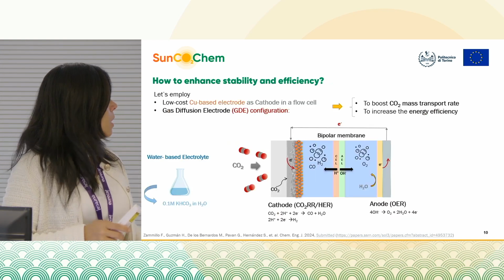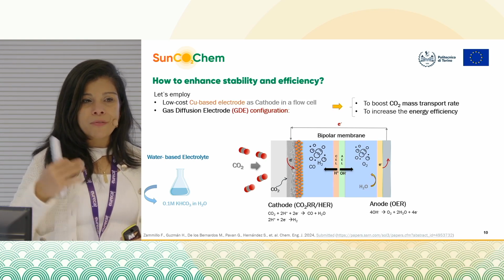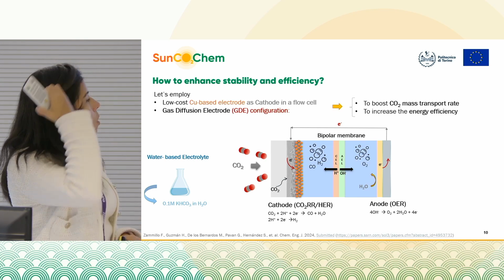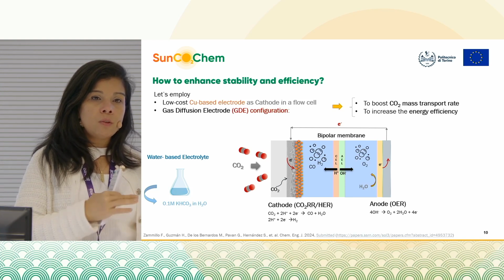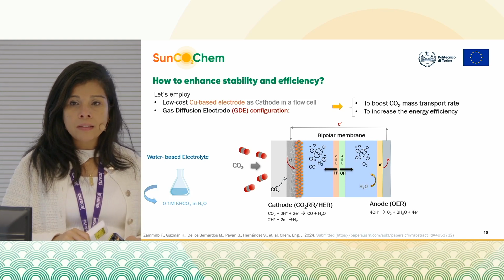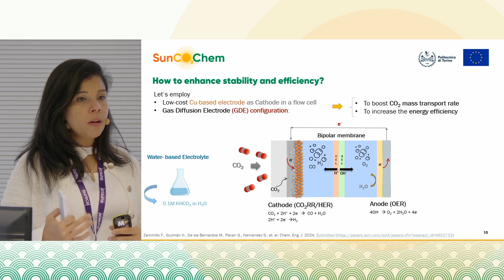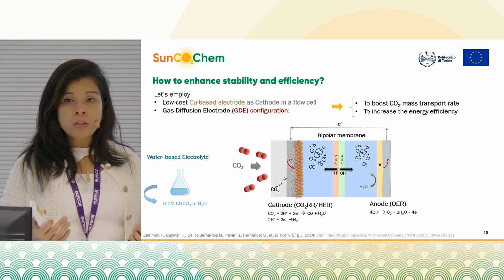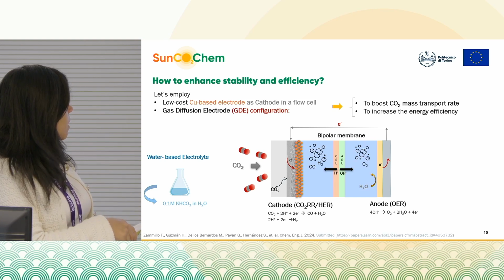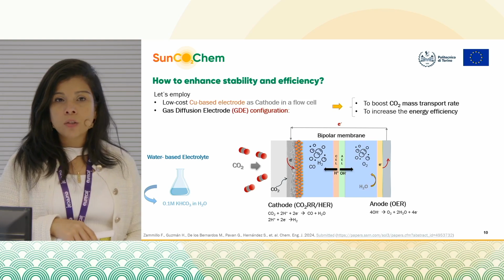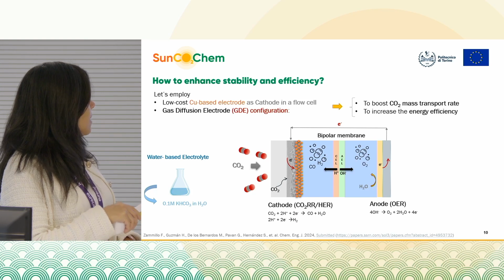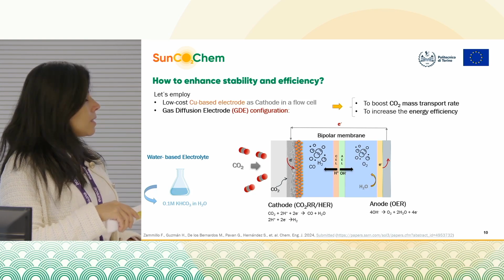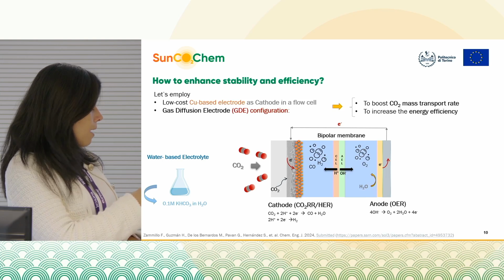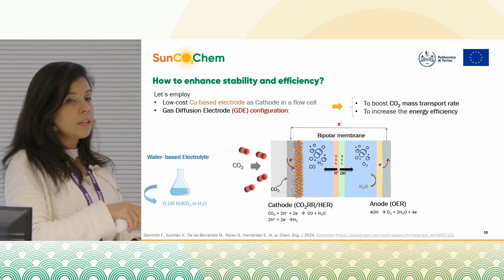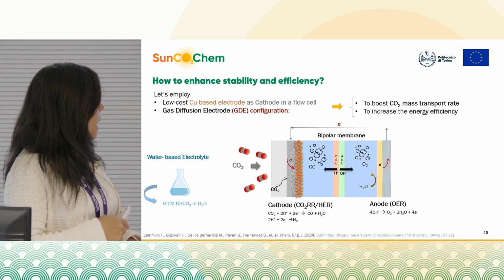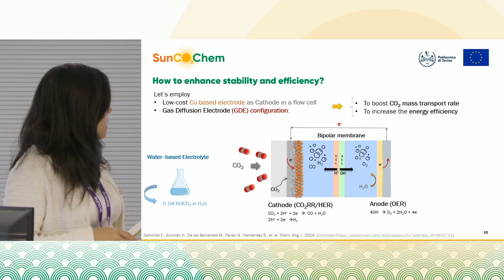So for that reason, and to go ahead with the goals of the project of demonstrating a high scale syngas production, we decided to shift towards the utilization of an aqueous-based electrolyte. But in this case, to tackle the problem of the low solubility of the CO2 in the water media, we decided to use a gas diffusion electrode configuration that entails the direct feeding of the gaseous CO2 to the backside of our electrode, so as to have a high concentration of CO2 on the surface of the catalyst and allow a good conversion of the CO2 in this kind of system.